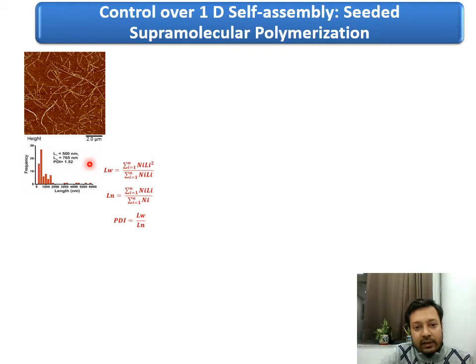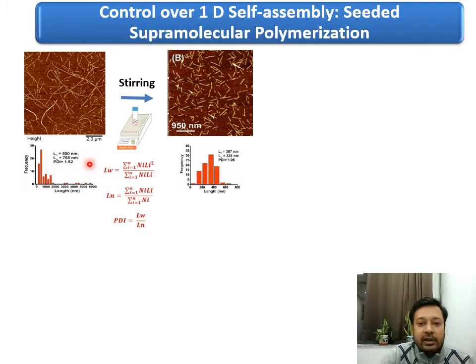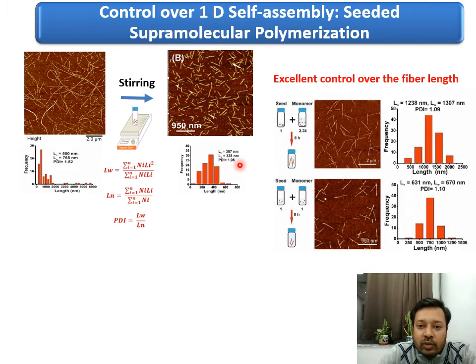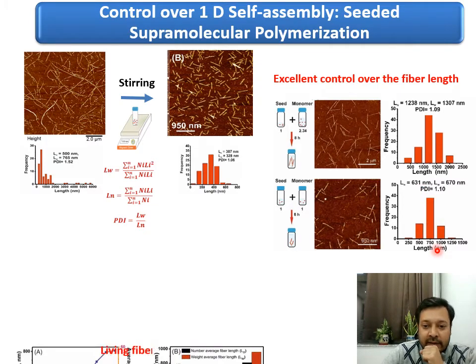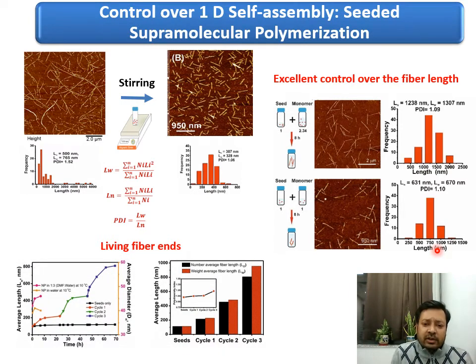So then we thought that if we can make a very nice uniform seed, that would be excellent. So we formed seeds of lower PDI, close to 1. Now these seeds we employed with different ratios of nanoparticle to form different length distributions of the resulting fibers, which we also looked into using histogram analysis. We could see that we can make nanofibers of 1.2 micron or around 600 nanometer based on the ratio of monomer and seed. And such nanofibers or seeds are living in nature.